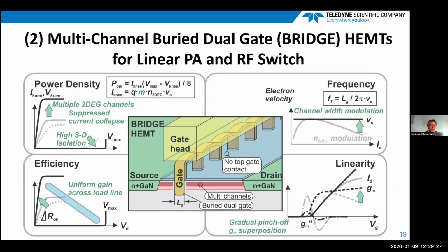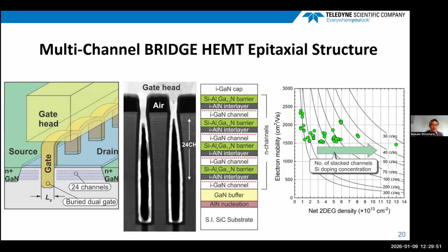So the transistor behaves like a MESFET, utilizing high electron mobility two-dimensional channels. The transistor current is modulated by modulating the width of the channels using this lateral gating. In the middle, I show the cross-sectional TEM image of the fabricated devices. This device has 24 channels. Each channel consists of silicon modulation doped AlGaN, an aluminum nitride interlayer, and the gallium nitride channel layer. And we stack these structures on top of each other. We can control the 2DEG density in each channel by the silicon doping concentration, as well as the number of total channels.